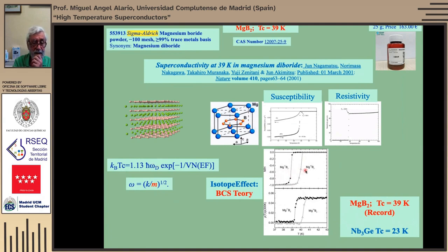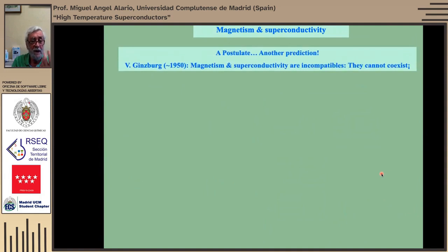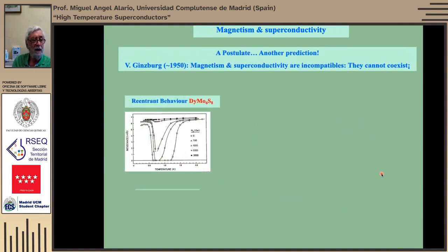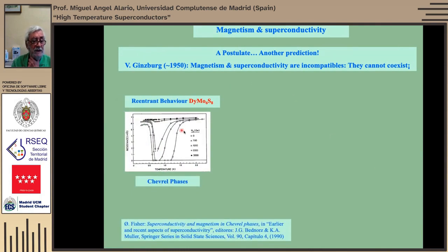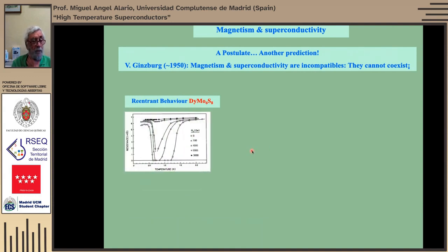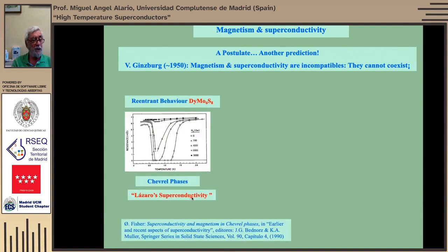And you can see that here. That changes the mass of the boron isotope. This is another interesting mechanism in superconductivity. Anyway, another prediction. Magnetism and superconductivity are incompatible. However, there are materials like this, which is superconductor, and then if you cool down, superconductivity reappears. These particular materials show the so-called reentrant behavior. But another nicer thing to call it is Lazarus superconductivity. I'm sure all of you know in the Bible that Jesus is able to resuscitate Lazarus. And so here, as it reappears, this is called Lazarus superconductivity, a very funny denomination.